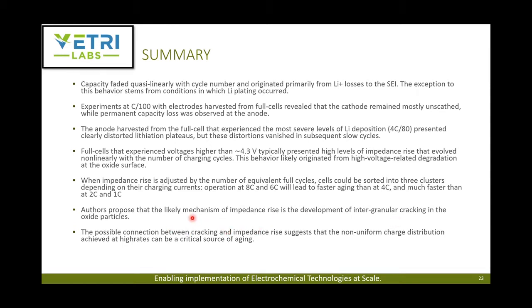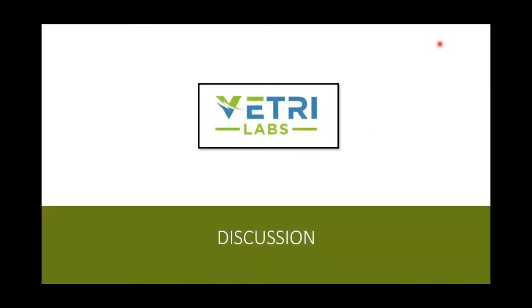Intergranular cracking of the oxide particles is what they're hypothesizing. And the possible connection between the cracking suggests that local non-uniformity is what leads to the aging on the cathode side. So that's the summary, and now it's open for discussion, comments, questions. I can bring up the charts later.